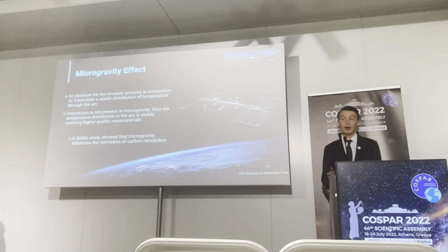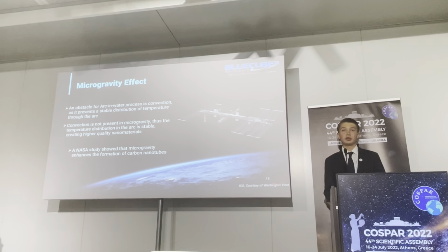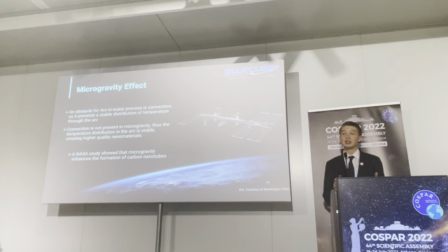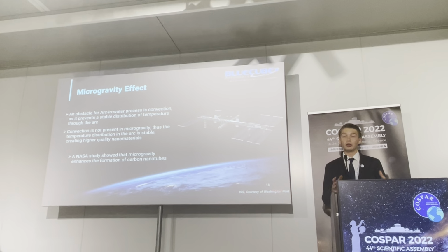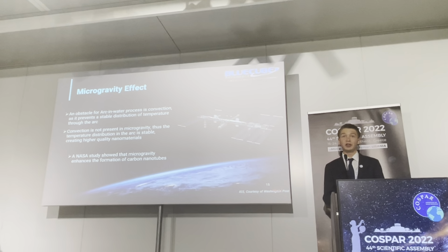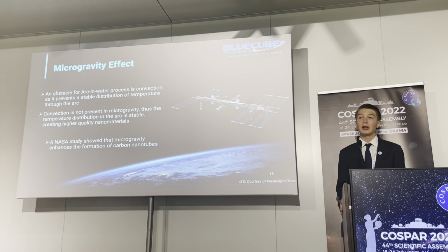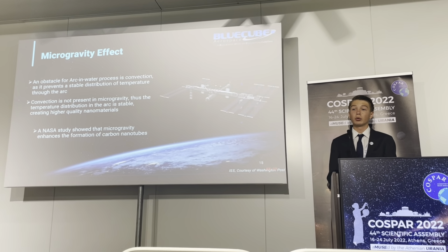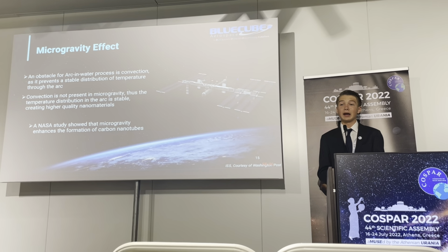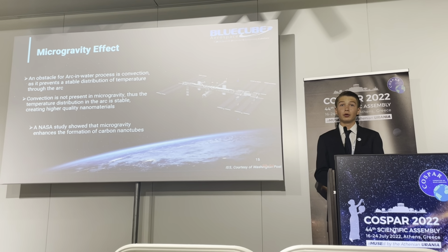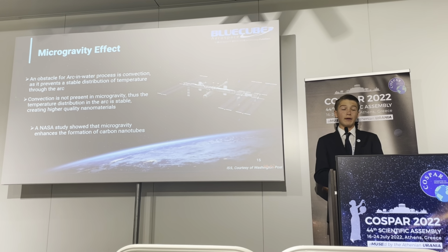In order to do this, they created a simplified arc in liquid apparatus, and then used the drop chamber to simulate the microgravity environment. This presents a series of challenges in and of itself, since in the drop chamber there's obviously only a limited amount of time that the experiment can be conducted, so they're only able to collect 2 to 3 seconds of data, meaning that the experiment's not as thorough as it could have been. However, it was still found that the microgravity environment can positively impact the formation of carbon nanotubes.